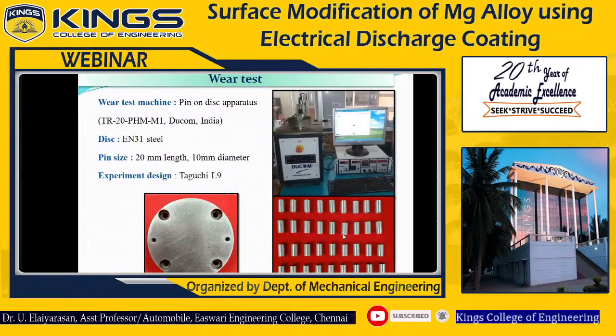A wear testing machine, a pin and disc apparatus, has been used for conducting the wear test, with an EN31 steel disc. The pin size of the coated surface is 20 mm length and 10 mm diameter. For conducting the Taguchi technique, the L9 Taguchi orthogonal array has been used to conduct the experiment.